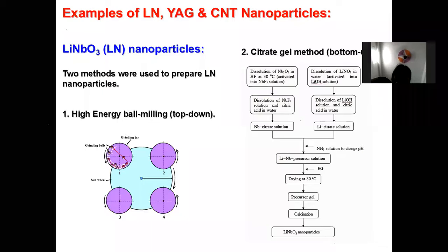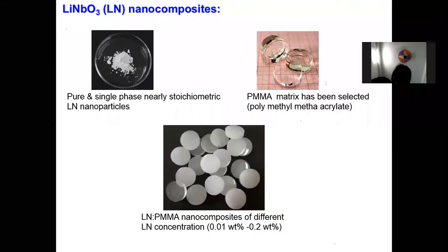So the technique for making this is, one is high energy ball milling, top down, and the other is the bottom up sol-gel method. This is how we made this material, and then made the nanocomposite. So these are pure, single phase, nearly stoichiometric nanoparticles we have made by both techniques, either top down or bottom up.